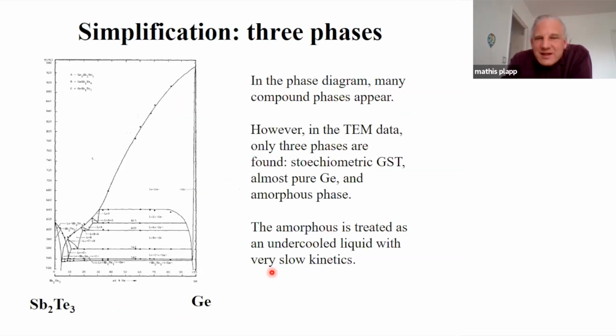Then we need to have an idea of the phase diagram. So here is a two-dimensional cut with axes temperature and composition. It's not exactly the cut we need, but still we can see that here is pure germanium, and we have a solubility with a liquidus that goes down here. Here's the pure GST phase. And if we enrich this in germanium, we also have a liquidus that goes down in the other direction. So this is a phase diagram of eutectic type.